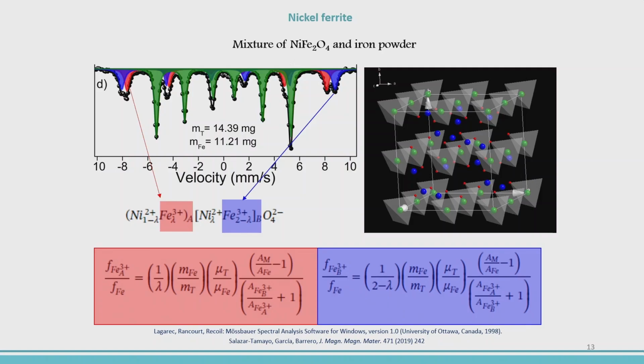Now let's show you here an example for another ferrite, that is nickel ferrite. Look, we have to start with what we assume is the formula for the distribution of the iron. This is important. This is the starting point. This is what we think is happening with the sample. And then we use the previous equation, and we derive these two equations to determine the recoilless factor for the irons in the two sites for this ferrite. You notice that this formula is different from that of magnetite. I hope you notice, especially in this factor here.